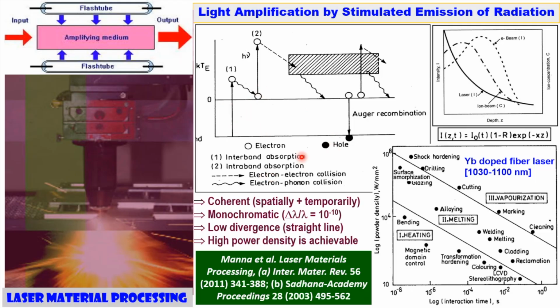The entire process of intra-band or interband transition and subsequent absorption of energy is very fast, on the order of nano to picoseconds. As a result, you absorb the energy in the shortest possible time. The advantage is that compared to electron beam or ion beam, laser energy deposition follows an exponentially decaying profile, meaning that as a function of depth, the energy is absorbed highest at the surface and then decreases very soon.